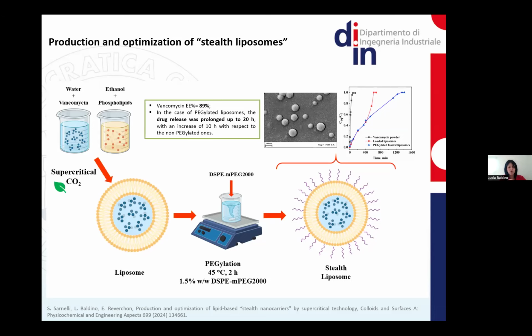So in order to avoid this problem, generally the external surface of liposomes is coated by using hydrophilic macromolecules or biopolymers like polyethylene glycol in order to create a thin water layer around the liposomes. Operating in this manner, opsonins, that are proteins of our plasma, cannot recognize liposomes, and therefore they have a longer residence time to reach the target site and release the drug.